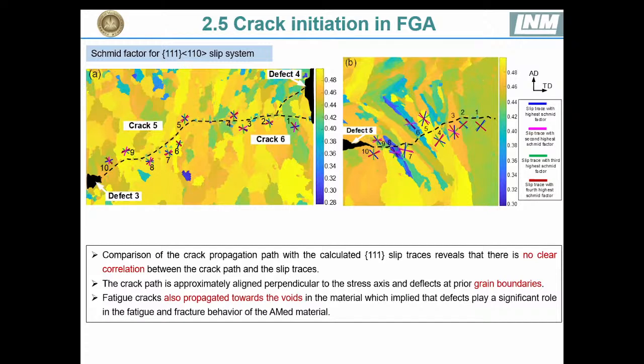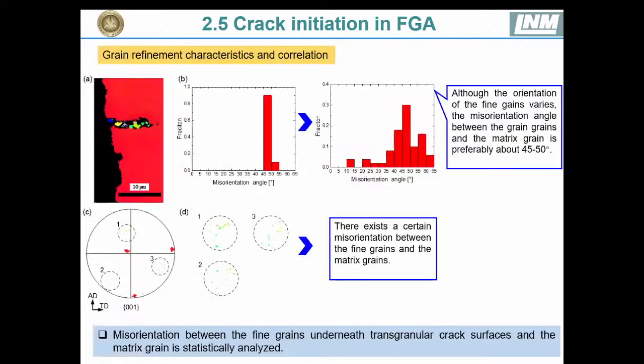And fatigue cracks also propagated towards the void in the material, which implied that defects play a significant role in the fatigue and the fracture behavior of the AM materials here. And the grain refinement in very high cycle fatigue is also a high angle boundary formation mechanism. And here the misorientation angle between fine grains and the matrix is also analyzed. And here we can see there exists certain misorientation between the fine grains and the matrix grains.